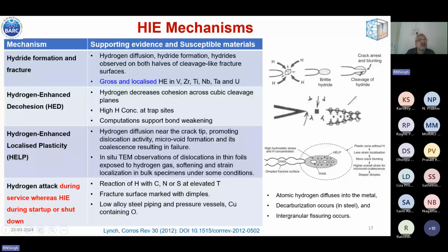The third one is hydrogen enhanced localized plasticity. Here hydrogen diffusion near the crack tip takes place, promoting the dislocation activity and microvoid formation and coalescence resulting in failure. In situ TEM observations experimentally support this, the movement of dislocations in thin foils which are exposed to hydrogen gas. Softening and strain localization in bulk specimens under some conditions has also been observed. So the dimple fracture surface is observed in this kind of failure. So this is the plastic zone without hydrogen and the plastic zone with hydrogen where voids have already formed.